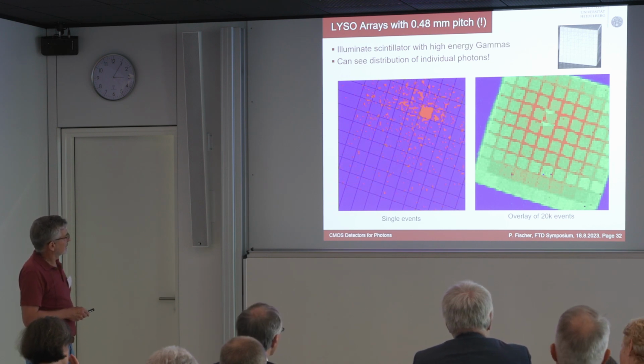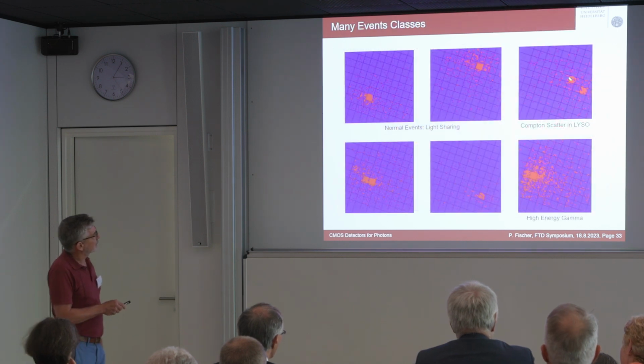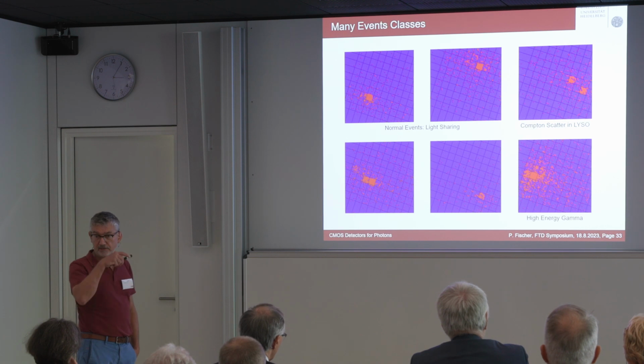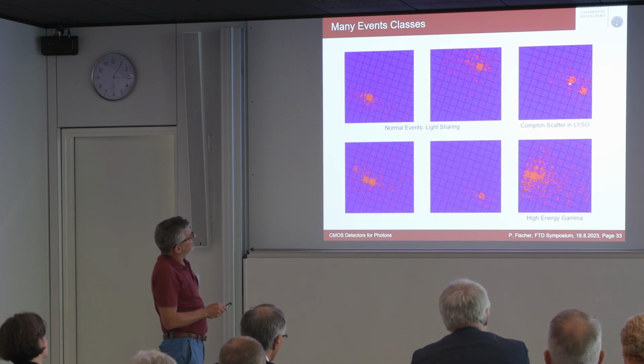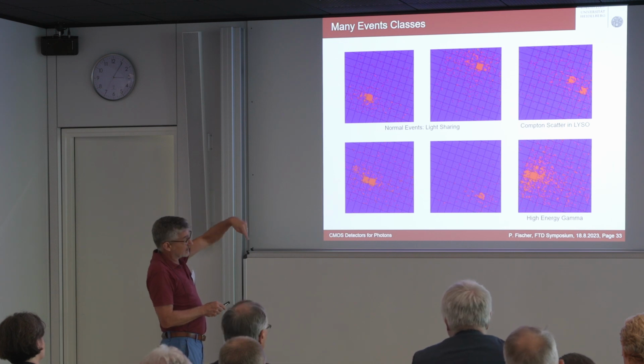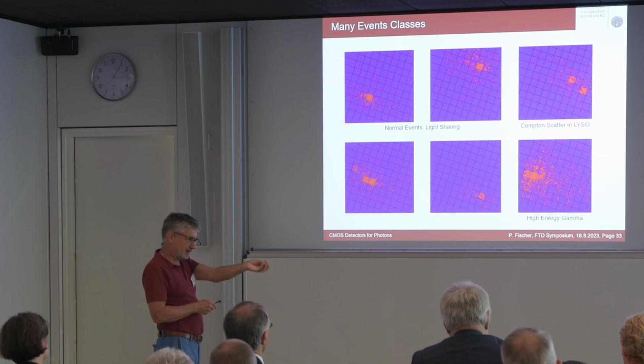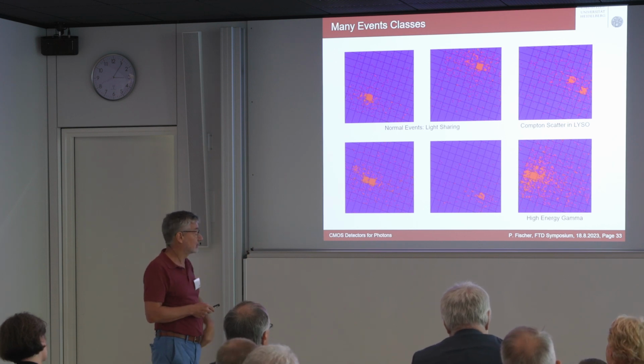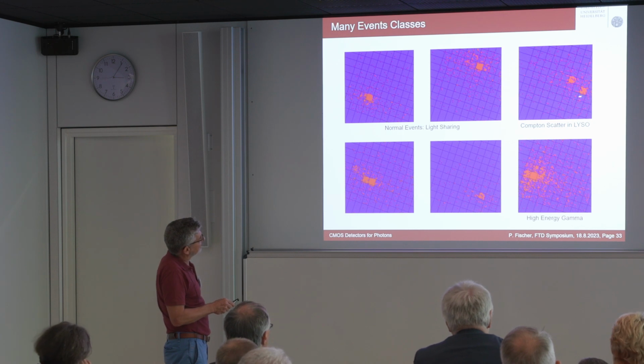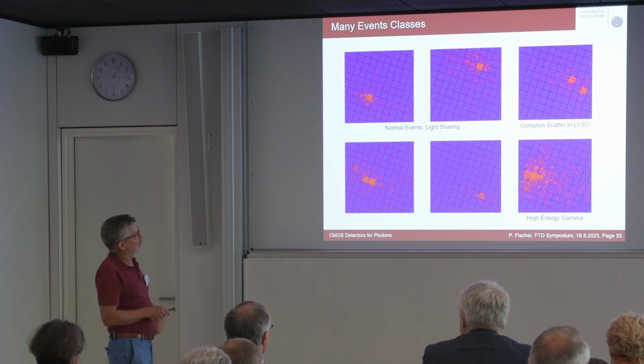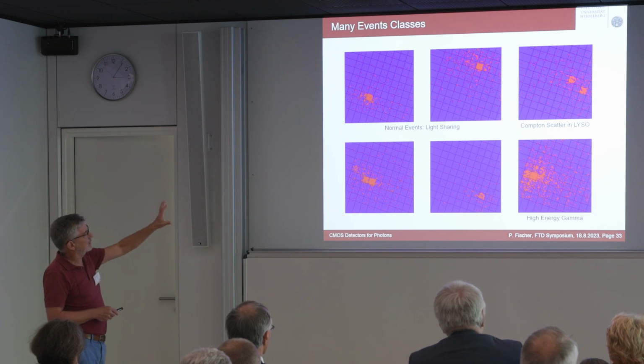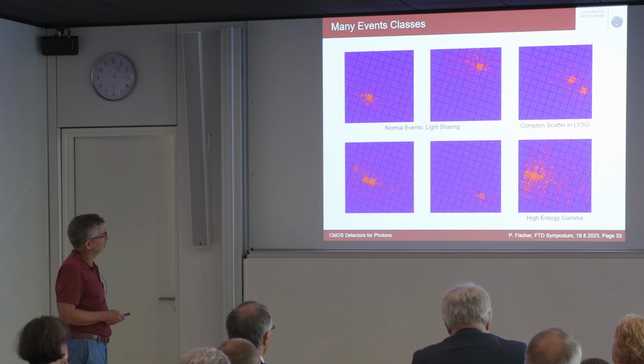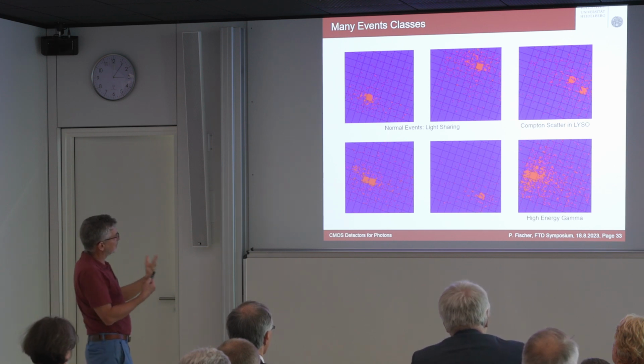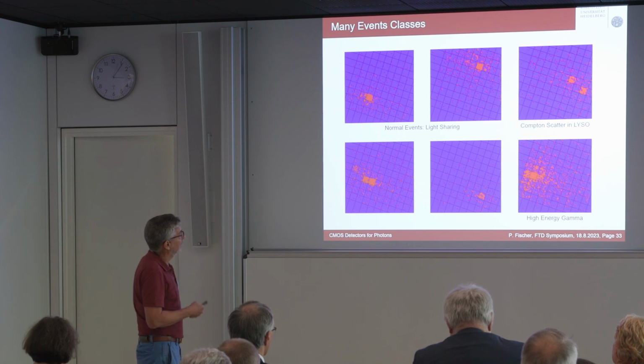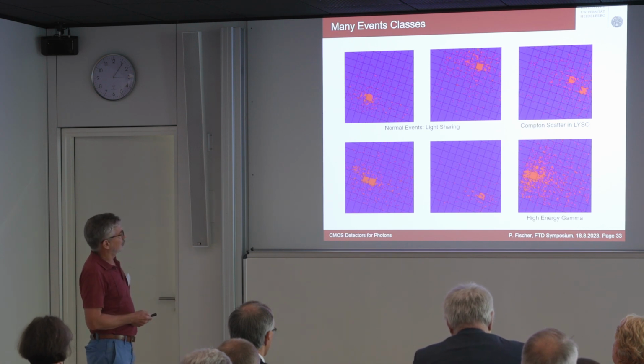And you could do some interesting physics. For instance, these types of events happen quite often, and these are Compton scatters in the LYSO. The gamma is absorbed in one crystal, but it's not fully absorbed, it's partially scattered, so it produces a fractional signal, and there's still a gamma continuing on. And then eventually this residual gamma is absorbed in another crystal. This is a problem because it degrades the spatial resolution. But with such a detector, you could eventually try to reconstruct these Compton scatters and improve the resolution. So this is a nice example that this imaging possibility really gives you quite some opportunities to do new things.